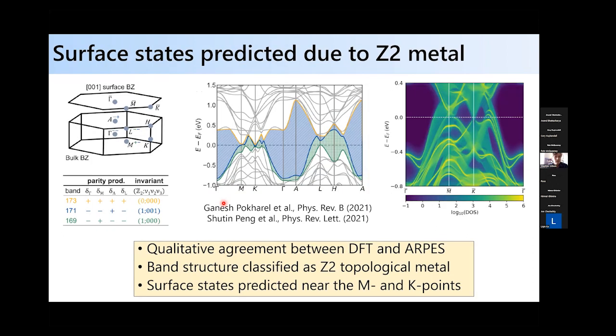Okay. So another wrinkle is that the surface state is predicted to be close to the Fermi level in these systems. They're technically Z2 topological metals, so one can do the standard band structure classification of these systems. And there's some hint that some of these topological surface states may be there from photoemission measurements by Junfeng He's group. But there are also a number of trivial surface states that come from the tin states in this material.